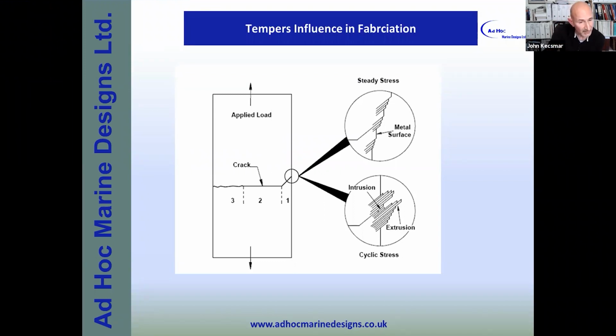So this means, for example, when you're starting to roll that plating for the jet duct, if you leave even one small score mark, no matter how small, that is another dislocation. And so as it starts to flex, you're going to get under a microscope something that looks like the top image or the bottom image, where you can see the intrusions and extrusions of where the atoms are moving against each other up and down, rather like having a whole ream of paper and you're just sliding it back and forth in your hand. And this constitutes what is termed crack stage 1 growth. The initiation then goes to 2, then eventually failure in 3.